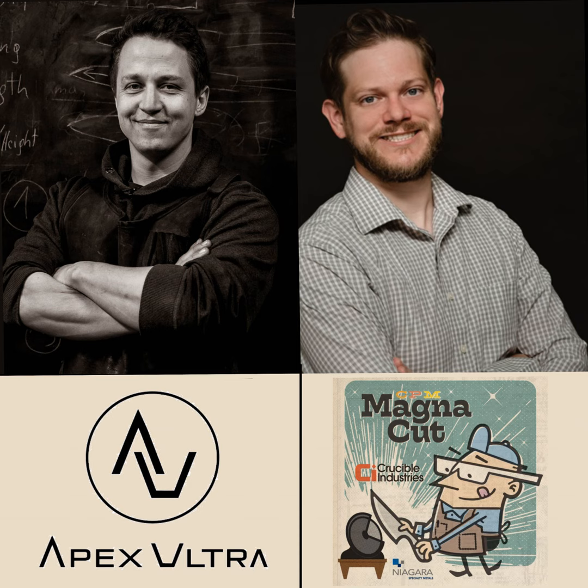Of working, yeah. So they're all basically just making an oxygen barrier to a certain temperature. They all try to remove the oxygen. So you want two metallic surfaces touching each other, and there are various different ways of achieving that. One is burn more fuel than air, and you have less oxygen in the mix. One is add an oil or graphite powder or whatever, so there's more carbon, so there's more fuel to the air that's touching it, until it's all burned, then it's all away. So it doesn't form a permanent layer. It just helps to reduce oxidation.